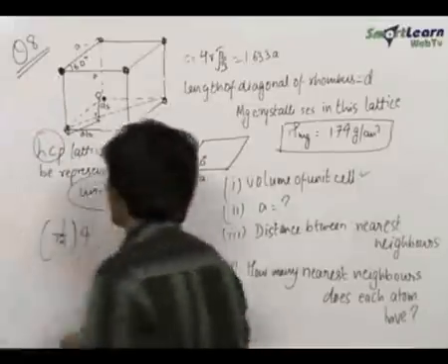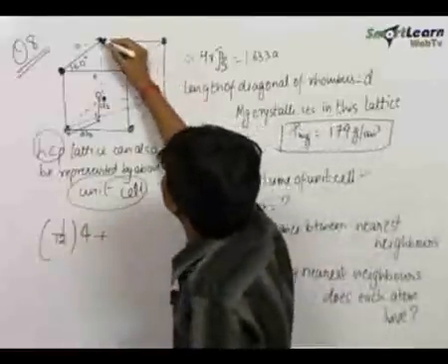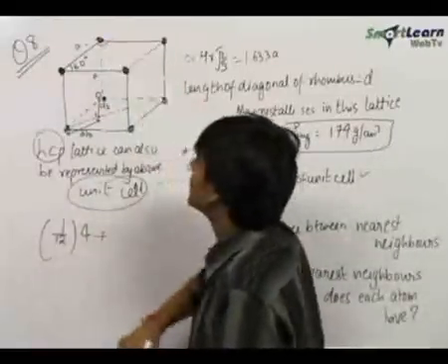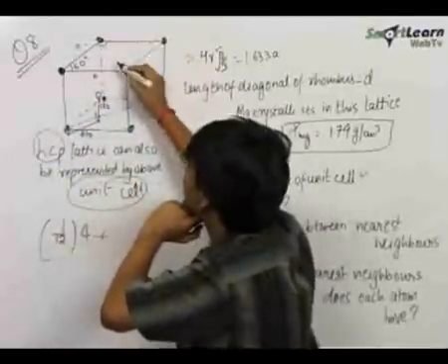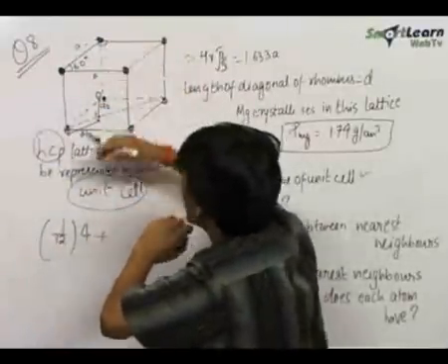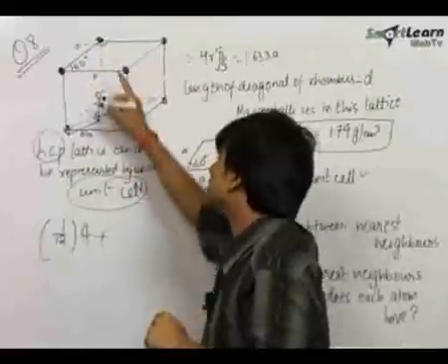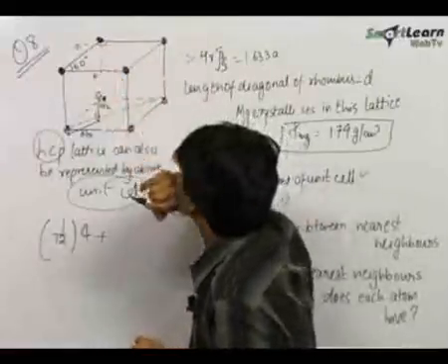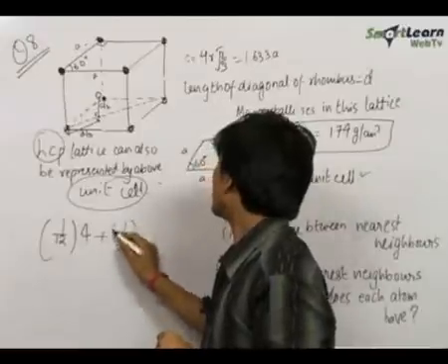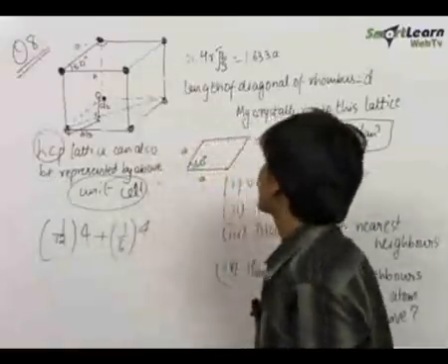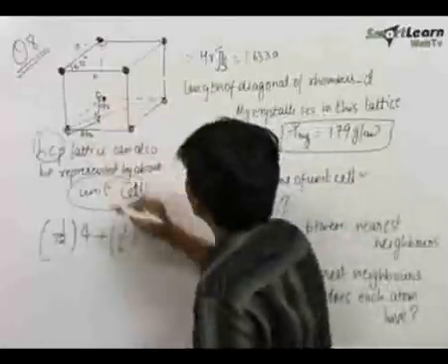There are 4 atoms at corners where the angle is 120 degrees. Three other unit cells in this plane, making 360 degrees, share this atom, and there are 3 other unit cells above, giving a total of 6 unit cells sharing it. Therefore, the contribution of each of these atoms is 1/6. There are 4 such atoms at these positions. The central atom has a contribution of 1.